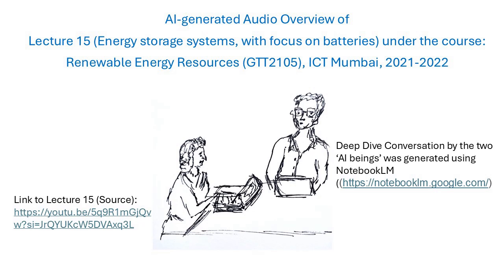To illustrate primary batteries, he talks about the zinc-air type. Those are neat. Zinc metal anode, but the cathode uses oxygen from the air. Yeah, there's a special membrane, often PTFE, that lets oxygen in but keeps the gooey electrolyte inside. Zinc reacts, oxygen reacts, you get zinc oxide. And about 1.6 volts. But it's primary because making zinc oxide back into zinc isn't easy electrically. Once the zinc's used up, it's done. A good example of a high-energy primary cell.